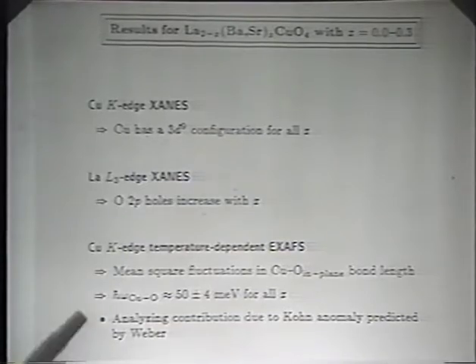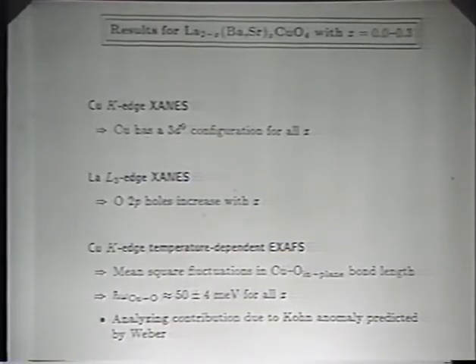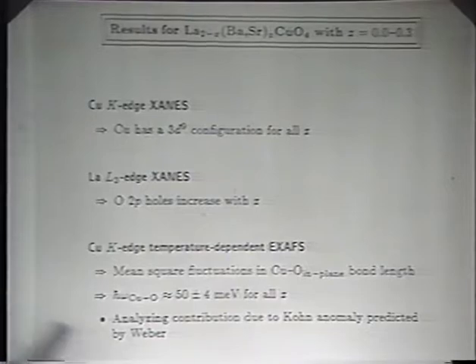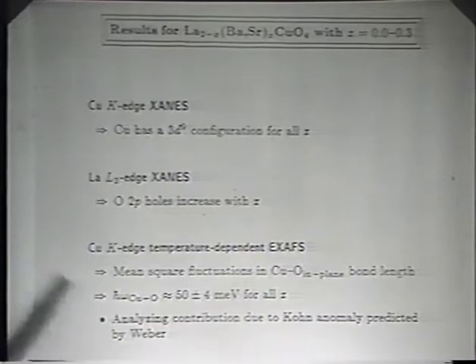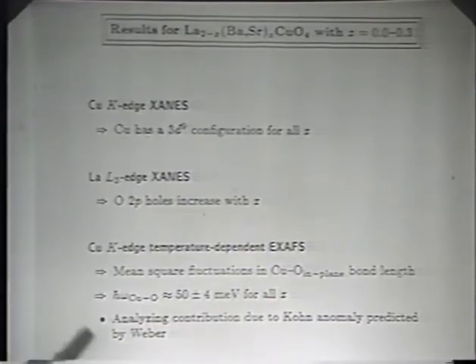So we're presently analyzing our Debye-Waller factor information to see whether we're sensitive to the Kohn anomaly contribution calculated by Weber. At the moment, we think we are sensitive to it, and our feeling is that we aren't seeing any significant softening of the phonons due to electron-phonon coupling. So thank you.